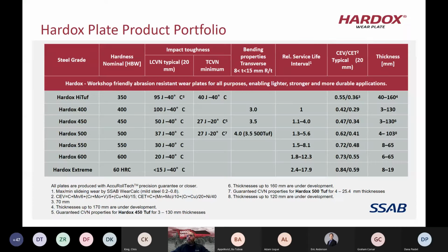Some of the Hardox plate products, we have anything from what we call Hardox HiTuf, which is around 350 Brinell hardness, all the way up to what we call Hardox Extreme, which is like 60 Rockwell C. And the plate thicknesses, we have anything from, say, 3 millimeter all the way up to a little over 6-inch thick plates, depending on the grade. But like a Hardox 450, we can make it from, say, 3.2 millimeter all the way up to, I think, a little over 5-inch, maybe even 6-inch today.